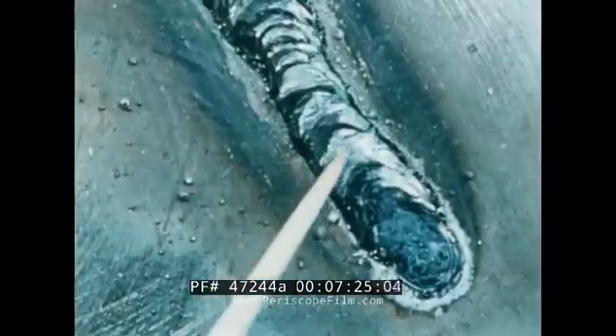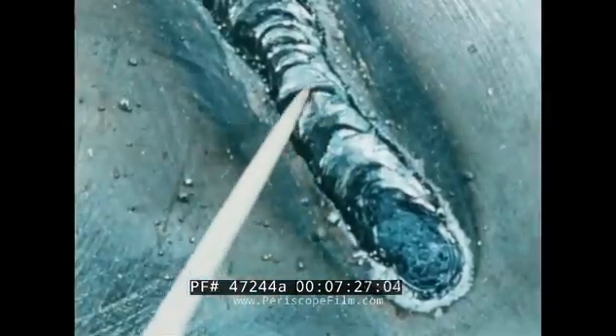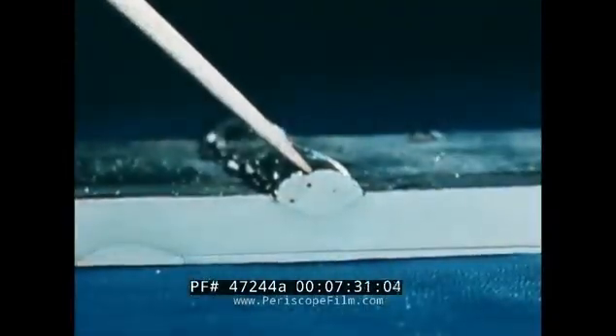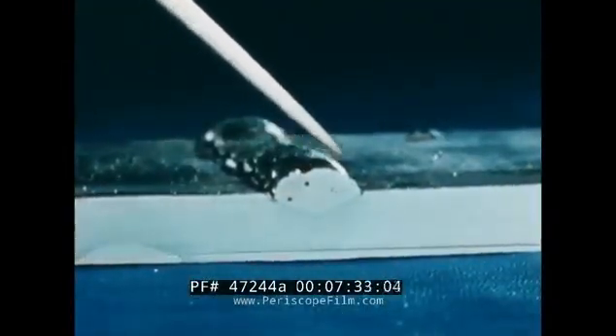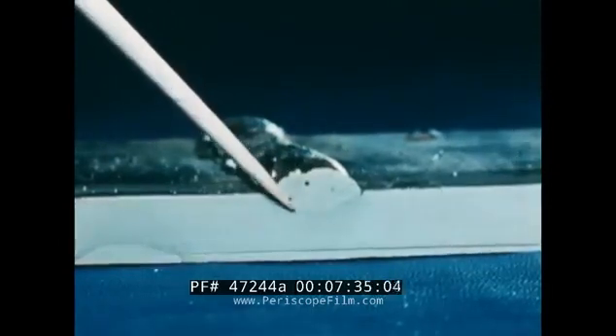The arc itself will have a tendency to short out and allow the electrode to freeze to the work. The bead is uneven with irregular ripples. It is high. There is poor fusion, and note the gas and slag inclusions.